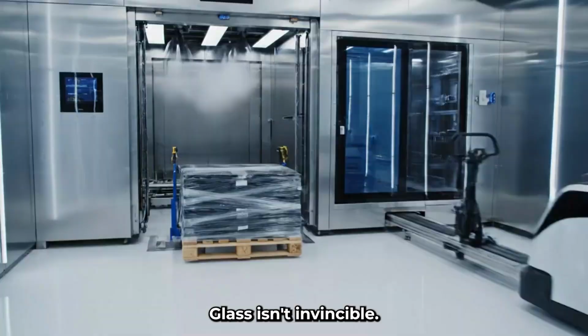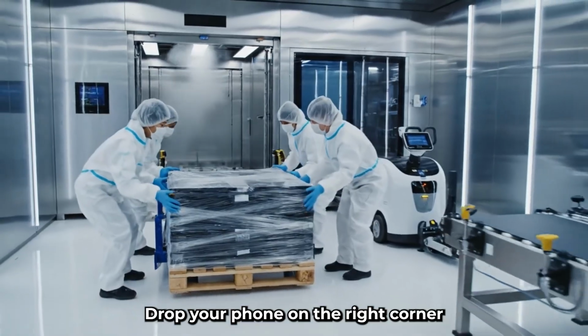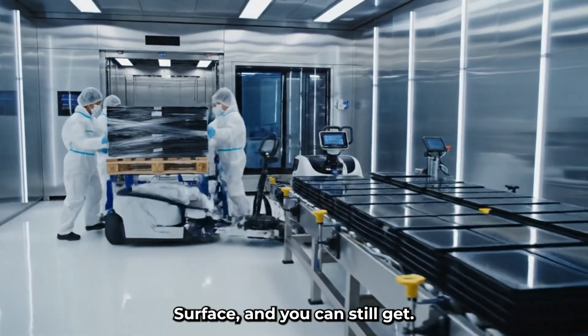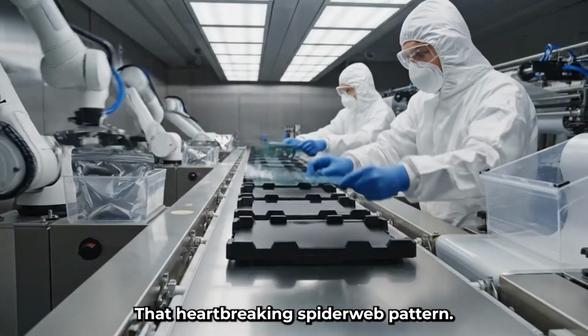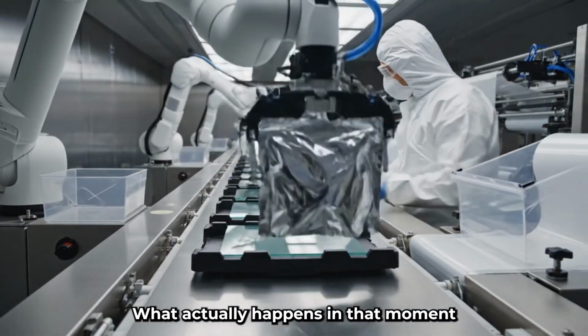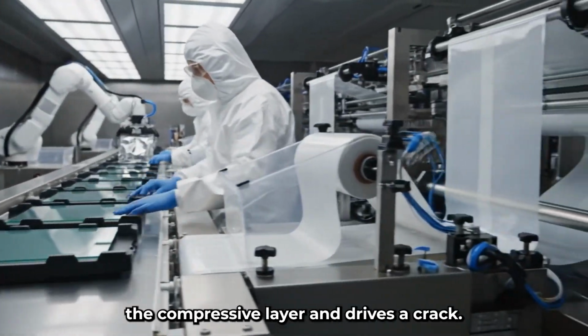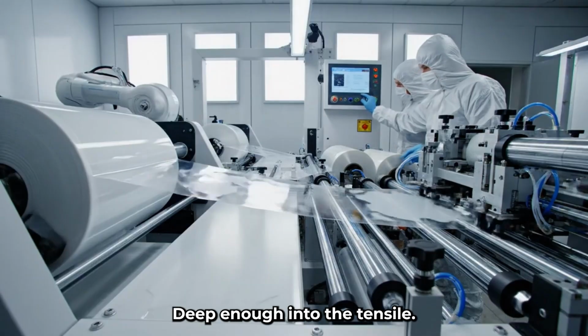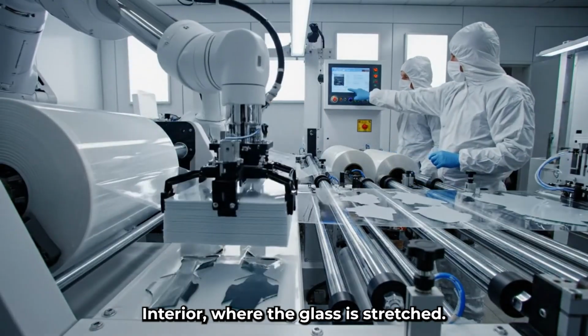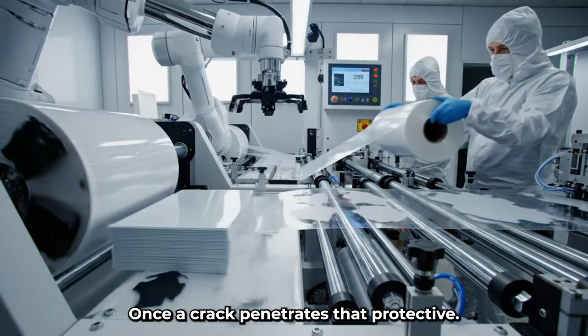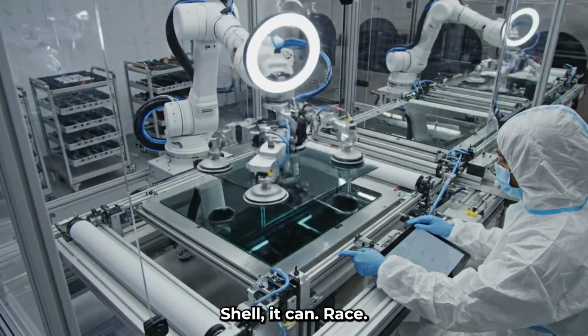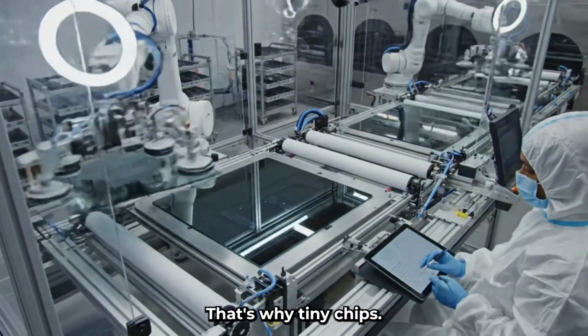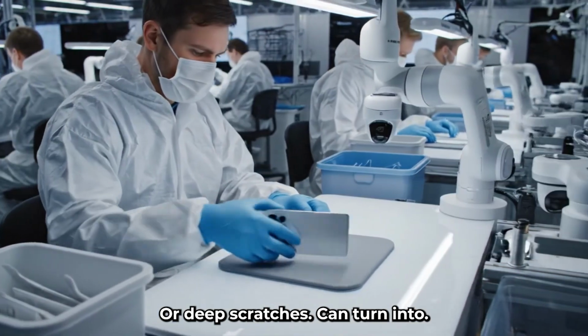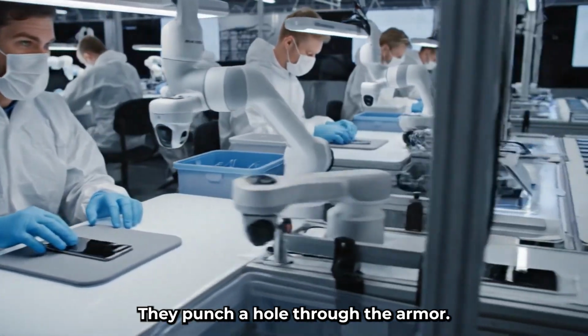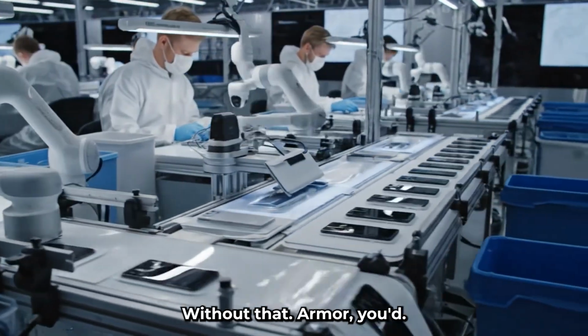Of course, Gorilla Glass isn't invincible. Drop your phone on the right corner from the wrong height onto a hard enough surface, and you can still get that heartbreaking spiderweb pattern. What actually happens in that moment is that the impact finally overcomes the compressive layer and drives a crack deep enough into the tensile interior, where the glass is stretched instead of squeezed. Once a crack penetrates that protective shell, it can race across the pane at incredible speed. That's why tiny chips or deep scratches can turn into big fractures later. They punch a hole through the armor, but consider the alternative. Without that armor, you'd be seeing those spider webs a lot more often.